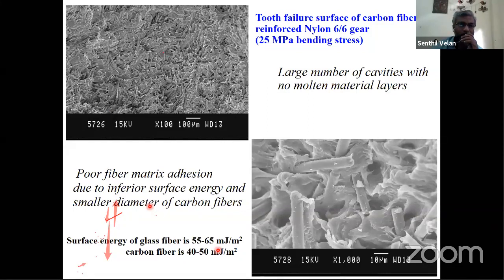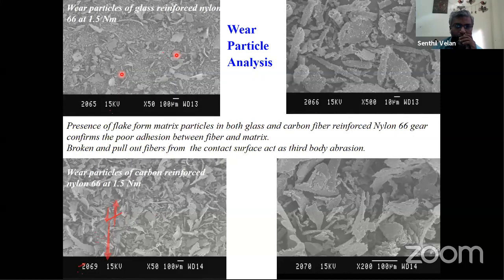So if you look at that, this also gives an idea about the wear particles. You must have seen the debris particles in the earlier slides for 6 material, whereas for the 6-6 material, you can see that the debris are larger in size, both in carbon and the 6-6 glass reinforced material. Even at low load contact conditions, you can see the wear debris particles. That means you have to limit your contact load even earlier than that. The carbon reinforced gears were having a better bending static strength. Though I have not presented that slide, as far as the contact condition is concerned, it was showing no bad crack. It takes more time to develop, to form, and to grow. That is sure. But it is a contact part. If you look into this, the surface is getting worn out very quickly.